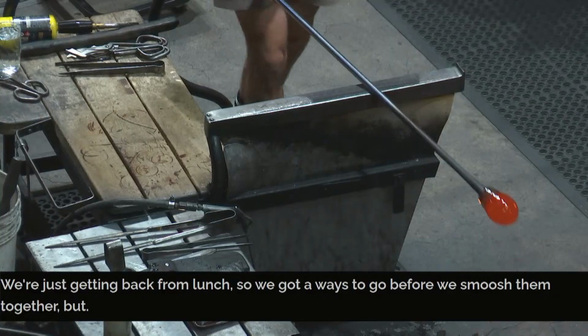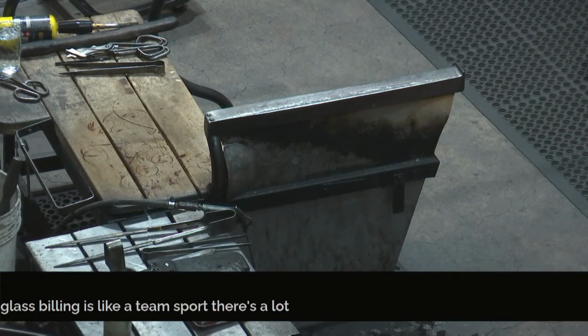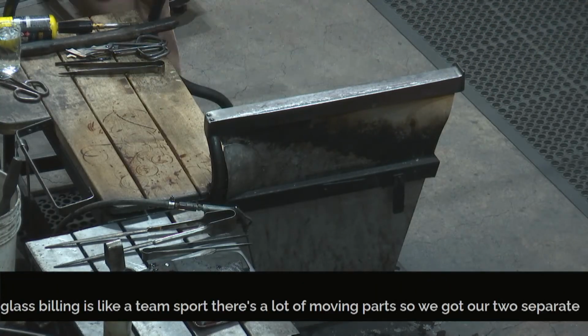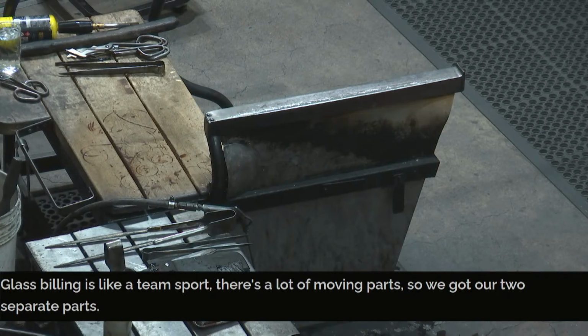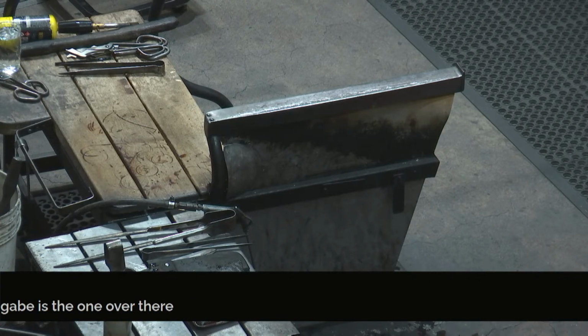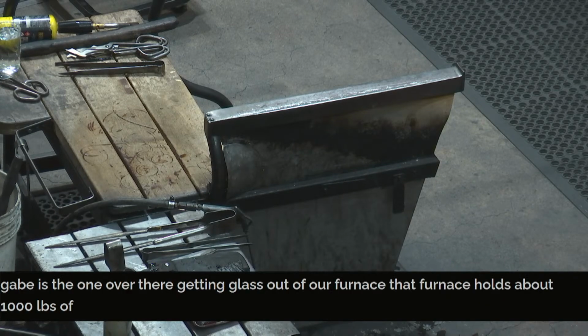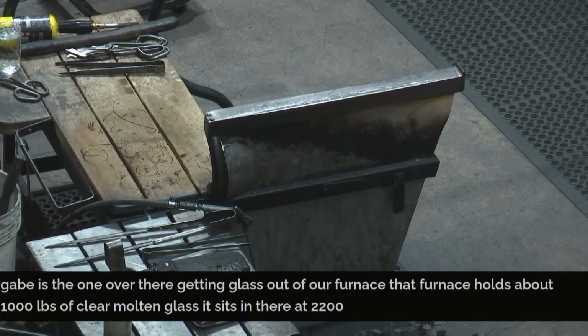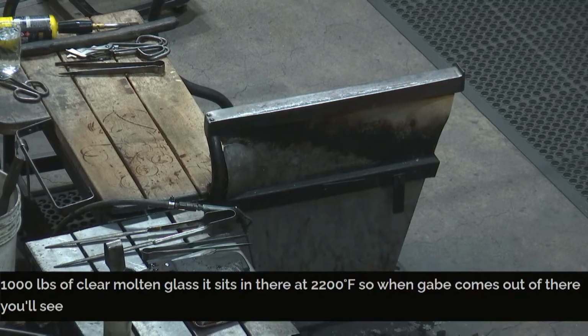Glass blowing is like a team sport. There's a lot of moving parts. So we got our two separate parts. Gabe is the one over there getting glass out of our furnace. That furnace holds about 1,000 pounds of clear molten glass. It sits in there at 2,200 degrees Fahrenheit. So when Gabe comes out of there, you'll see we've got a fresh layer of clear glass on top of this bubble.